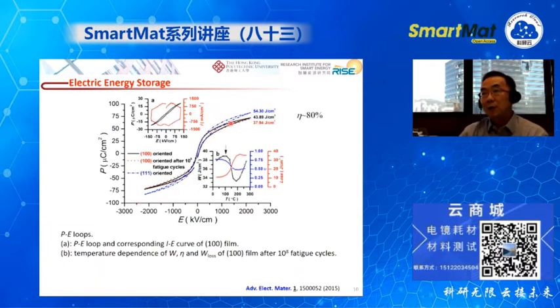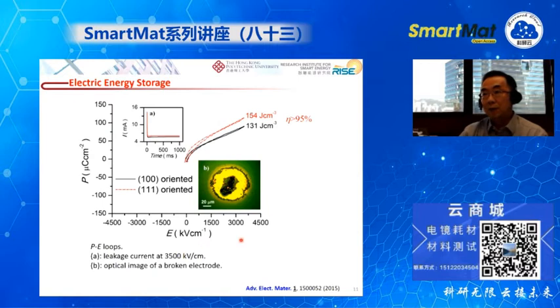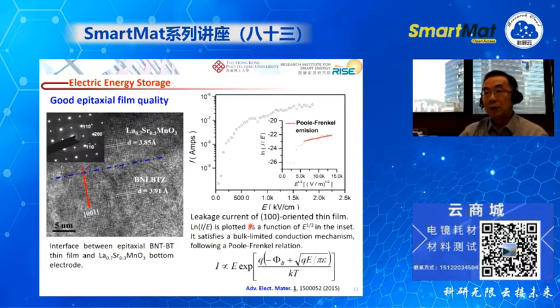Then we measure the P-E hysteresis loop. For different orientations of the film, you can see that we obtain a very high energy density. And if we further enhance the applied electric field up to 3,500 kilovolts per centimeter, we can see the obtained energy density can be even larger. And also the efficiency is very high, above 95%. This high breakdown field of the film is due to the very good epitaxial film quality.